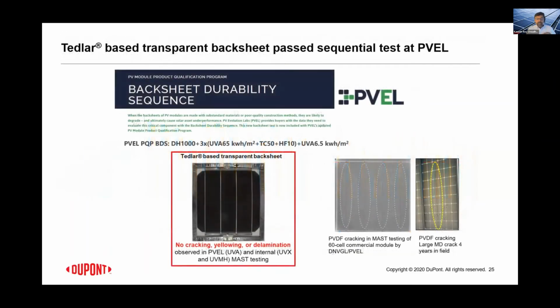And then finally, one of the other things that we definitely do, and we have been proposing this for quite a long time, as anyone in the industry in this area knows, we really believe that a true representation of the field is through a sequential accelerated test, and not just single stresses. And we have been pushing this for a long time. So here's one of the similar tests that's offered by PVEL in the US and over the globe. It's a combination of damp heat, cycles of UV and thermal cycle, and humidity freeze, as well as a short UV at the end.